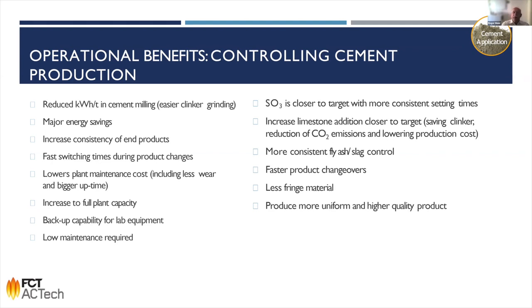Overall, by looking at all these parameters, it enables you to reduce the wear on all the heavy equipment by running a smoother process. And of course, the new cements, in particular, the things we heard yesterday, the PPC cement with fly ash addition or composite cements with fly ash and slag, these types of analyzers are very mandatory to be sure that the quality you deliver is in the spec and you give your customers the things they would like to have.